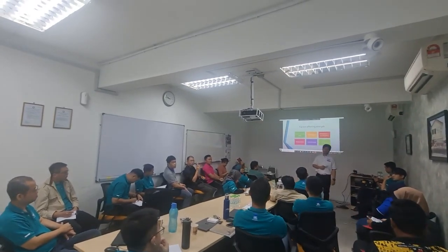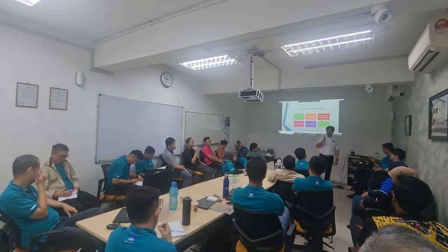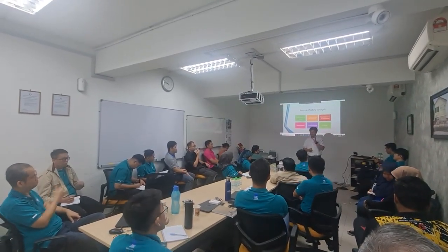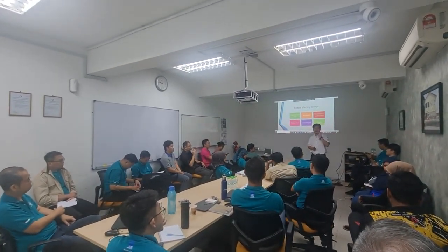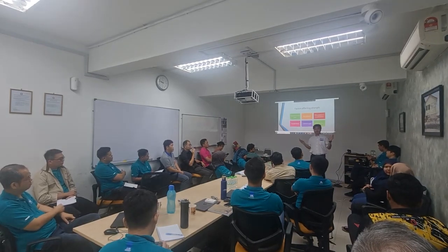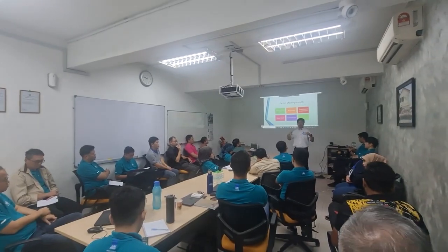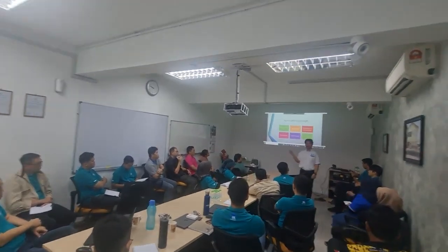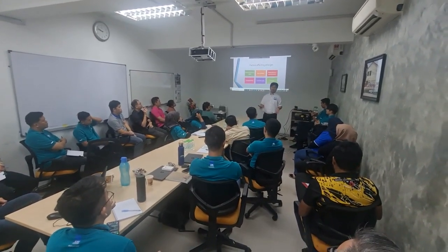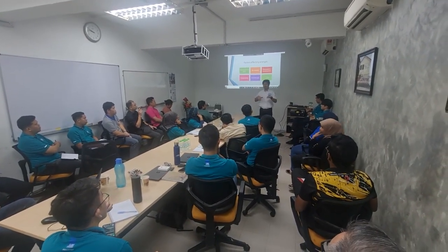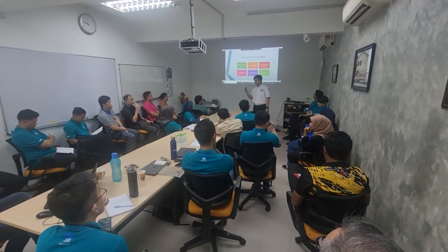But is it true that to a certain extent they actually want to create this air entrainment for pumpability? Air entrainment for pumpability is arguable. If let's say you ask me, I won't do it, unless you really want to entrain air for freeze and thaw. That means you are experiencing these freeze and thaw cycles, then you only entrain the air. But generally, your concrete will have air, maybe less than 2%, less than 1%, depends on your specifications, or 3%. Depends on your application. But generally, we do not want the air to be as high as 5 or 6.